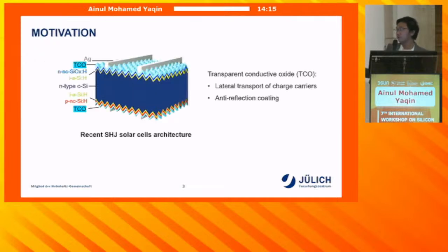If we look at recent silicon heterojunction solar cell structures, we start with the N-type crystalline silicon wafer sandwiched between intrinsic amorphous silicon layers, and on top of that, we usually have either nanocrystalline silicon or nanocrystalline silicon oxide. On top of that, we have the transparent conductive oxide layers, and finally we have the cells with the silver contact. The transparent conductive oxide layers, known as the TCO, act as lateral transport of the charge carriers, and also act as an anti-reflection coating to optimize the incoming sunlight being absorbed in the silicon wafer.